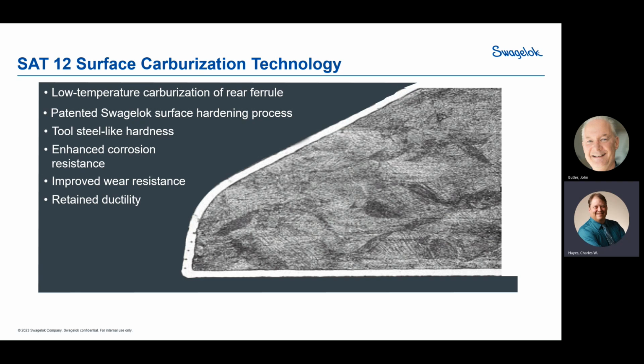What we do, so the basic process is you take the ferrules. Now, stainless is stainless because it's got a clear coating. So you can't see any corrosion because it actually is always corroded to a degree with a clear crystalline structure oxide layer that's on the outside. We strip that off in vacuum furnaces and are able to see the base material. In that base material, we force carbon into the surface at a very low temperature, not to create carbides, and we create a very, very hard surface.